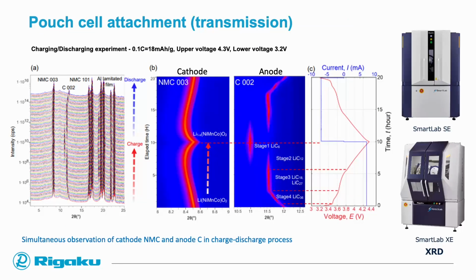For example, in this case, a pouch cell attachment in transmission geometry, we see a nice experiment of charging-discharging the pouch cell. To the left, we see the diffractogram of the corresponding phases. In the middle, we have two waterfall plots of interesting reflexes. The left one, the cathode, the NMC reflex, and to the right, the anode reflex of carbon. And the most right graph shows the charging-discharging cycle.